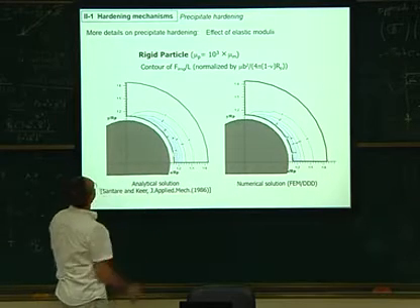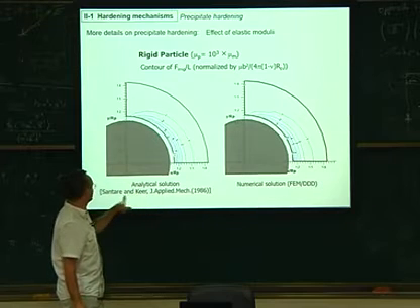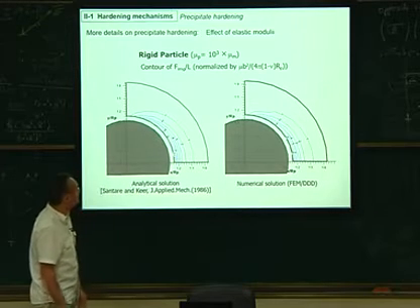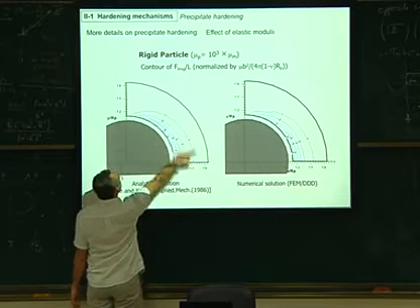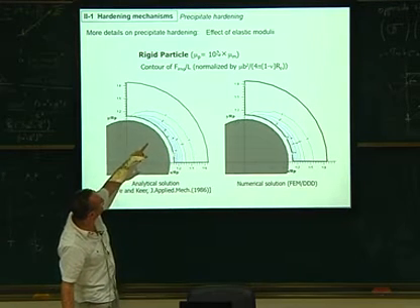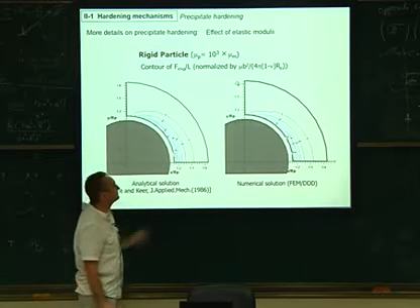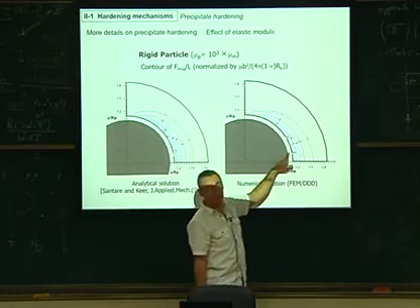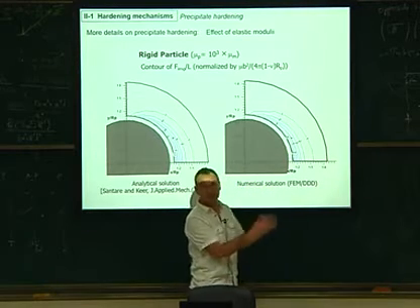So this one was 2D. There is an analytical solution that was given by Santare and Keer in 86. And you can see the evolution of the stress field, which looks like that. In this case, you have the particle, which is 1,000 times stronger than the matrix. So it is a repelling force. And this is the solution we got with the DD code. You can see that they match pretty well in that 2D case.